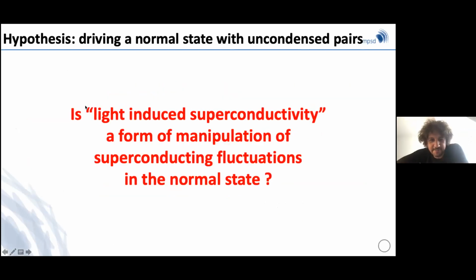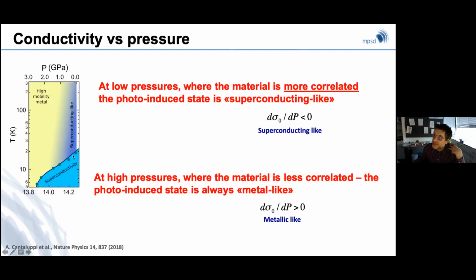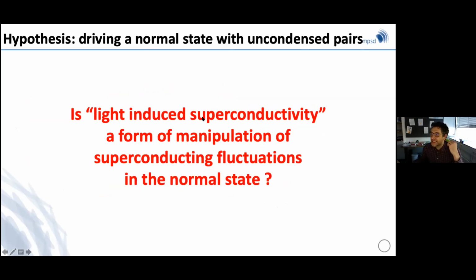Cool, sounds great. So the argument here is that because this effect appears to happen in the cuprates and in the fullerenes only in these regions close to, remember the phase diagram has a dome here and a Mott insulator here, only where the correlations are large enough, and we haven't been able to measure on this side, is light-induced superconductivity some form of manipulation of fluctuations of the normal state. And this is actually informed by other studies that we've been making a lot of progress on in the cuprates, collaborating closely with Eugene Demler's group at Harvard, where we've been making a number of critical assessments on the nature of the cuprate light-induced state.